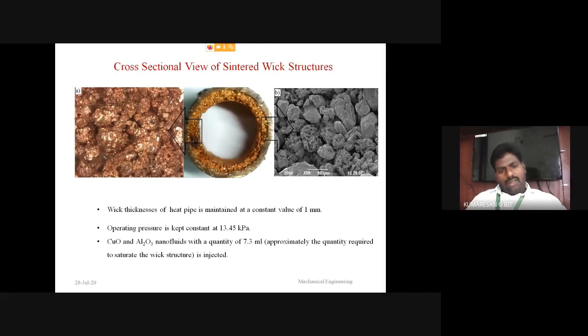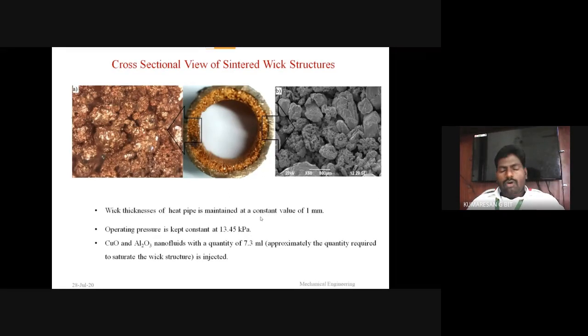Then the operating pressure of the heat pipe is kept constant at 13.45 kilopascal. You see here, if you want to boil water in the current atmospheric condition, we have to heat the water up to 100 degrees Celsius. Then only the boiling will take place. But this is for the 1 atmospheric pressure condition. Here you see that the working fluid is filled under a pressure of 13.45 kilopascal. At this condition, the water or nanofluid, CuO or aluminum nanofluid, can boil at 54 or 55 degrees Celsius, because the fluid is filled under a vacuum pressure. This vacuum pressure is maintained constant irrespective of the working condition.